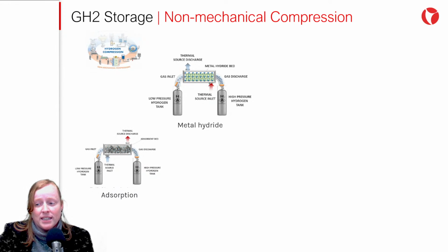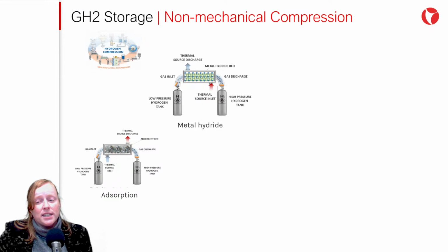Similarly, other compressors are being developed based on the adsorption of hydrogen in very porous substances with a high specific surface area. Low-pressure hydrogen is fed to a closed tank filled with a solid bed of the porous material. Heat is then supplied to the system, causing hydrogen desorption to occur at a higher pressure. By forming a stack of membranes, it's possible to reach up to 1,000 bar. The efficiency could reach between 70 and 80%. These compressors are compact and have no moving parts. However, the progressive degradation of the membrane restricts the useful life to well below that of a mechanical compression device.